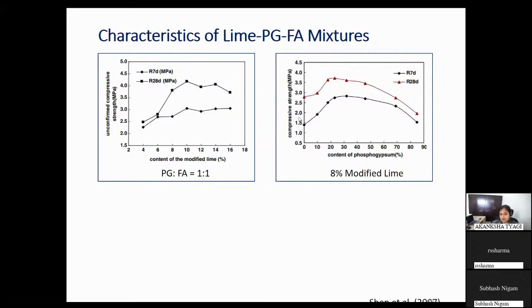And if you see the compressive strength with the 8% modified lime, as they increase the content of the phosphogypsum, because they are using phosphogypsum and fly ash mixtures, they found that up to 30% phosphogypsum, with around 70% fly ash and 8% modified lime, the compressive strength is the highest.